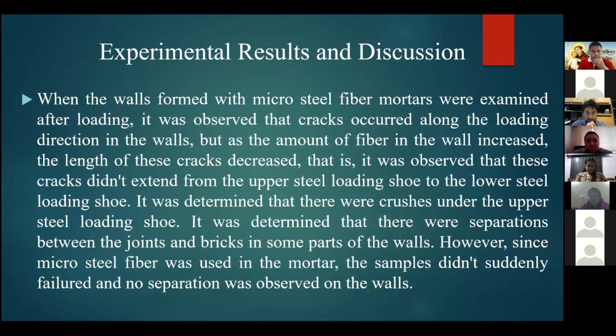When the walls formed with microsteel fiber mortars were examined after loading, it was observed that cracks occurred along the loading direction in the walls, but as the amount of fiber in the wall increased, the length of these cracks decreased. That is, the cracks didn't extend from the upper steel loading shoe to the lower steel loading shoe. It was determined that there were separations between the joints and bricks in some parts of the walls. However, since microsteel fiber was used in the mortar, the samples didn't suddenly fail, and no separation was observed on the walls.